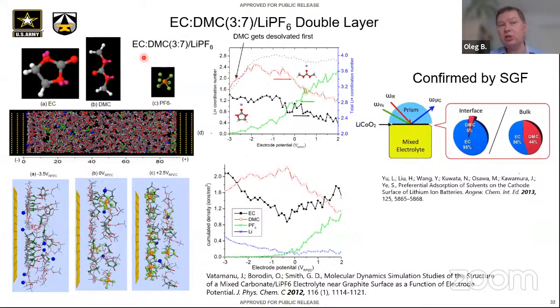However, if we take a traditional EC/DMC LiPF6 electrolyte, put it in between 2 electrodes, and start asking the question, what is the structure of the double layer? We do observe that at potential of zero charge, both solvents are present in proportional amounts of EC and DMC. There is some PF6 coming in, and lithium typically is not very close to the surface. Once we get to minus 3.5 volts, we do observe that lithiums are getting partially desolvated.